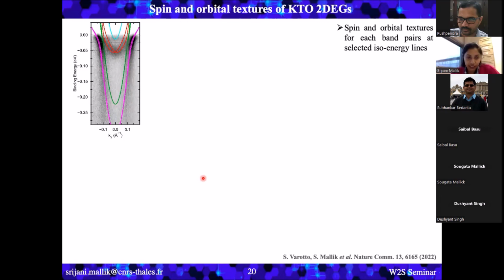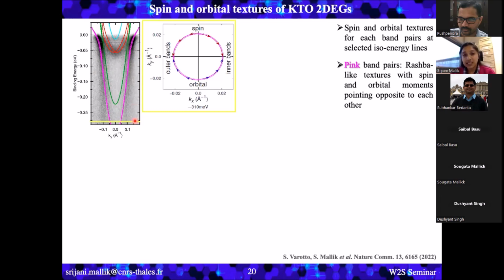So here I came back with the band structure I already showed you for the ARPES measurement and the tight binding fits. And from here, basically what we did is calculate the spin and orbital textures for each band pair at selected isoenergy lines. So very close to the band edge, we see that the Fermi contours are very nicely standard Rashba-like with the spin and orbital moments pointing opposite to each other.